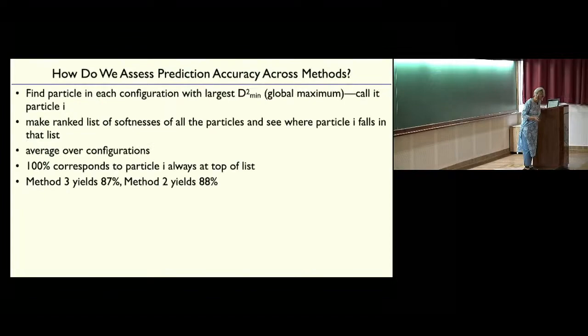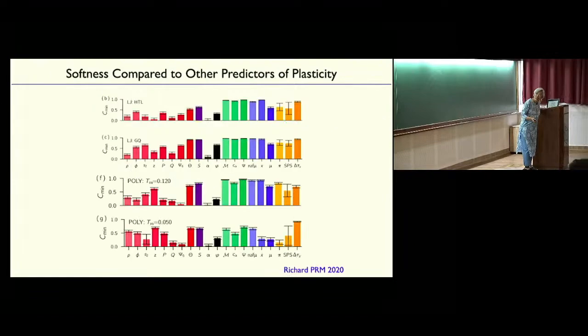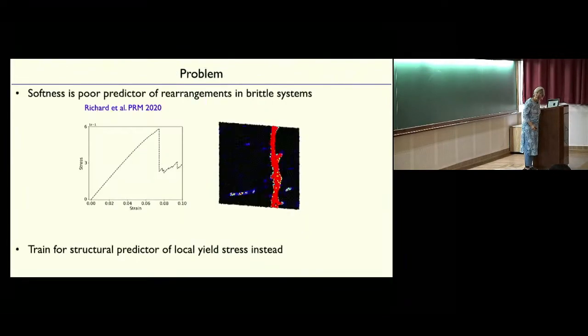Support linear, so we use support vector regression. One thing I do want to mention is that for the very brittle case of Ludovic's data, that has that huge stress drop, I'm going to skip all this in the interest of getting to the physics. In this case, it turns out that the softness really falls on its face. It's a terrible predictor. So we did something different. We actually trained a convolutional neural network.